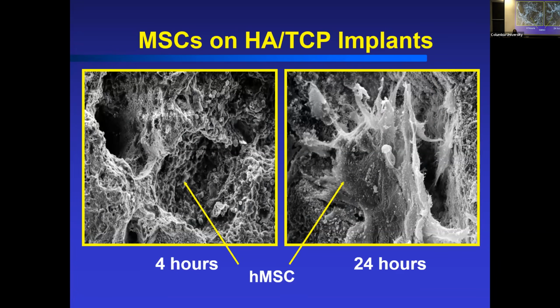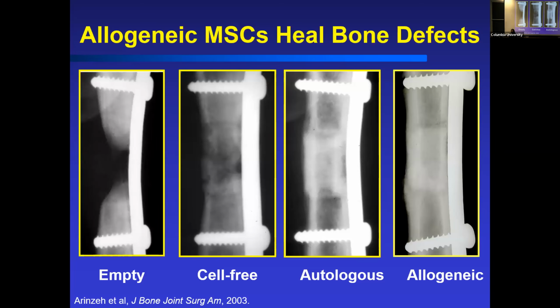And so our earlier work established that we can develop these bioceramics, these hydroxyapatite tricalcium phosphate porous ceramics that work well with these MSCs or stem cells, and that they allow for the attachment of these cells. If you notice the texture of these scaffolds, they have very kind of nano topography or porous topography, as well as these very large pores to allow for bone ingrowth and infiltration. But it's that nanostructure on the surface that allows for those cells to attach and differentiate. And so we've shown in models then, in particular this one, that we can use donor cells, these are allogeneic cells, or even, again, the autologous cells to repair these large defects.